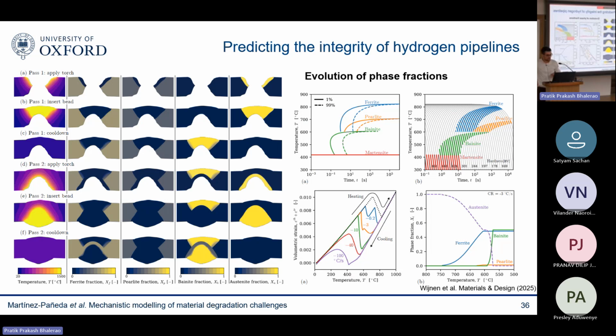But the beauty of it is that we can also account for the evolution of the phase fractions. So you can see here in this weld, this is again a 2-pass weld. You can see here the ferrite fraction, the pearlite fraction, the bainite fraction, and the austenite fraction. So depending on your cooling rates, depending on your composition, these welding models have been developed that allow you to predict this evolution of phase fraction. So we can predict the microstructural heterogeneity. And I was a bit suspicious at the beginning, saying, okay, yeah, but how do I know this is something that agrees with reality?